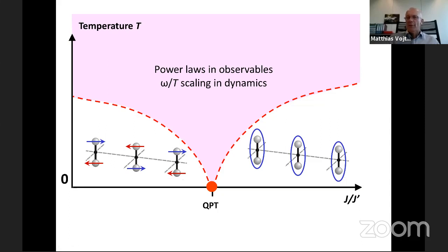There are various things one needs to consider. The first question, I guess, is does this ordered phase here on the left-hand side survive at all? If the answer is yes, there may be a different magnetically ordered state. For instance, instead of a square lattice, you can take a triangle lattice that's a bit frustrated, but there is still magnetic order. Then the phase diagram will qualitatively look the same. And since magnetic order is weaker, this phase transition point will move slightly to the left. So this phase tends to be suppressed with respect to this one. That is a quantitative change, but it's not very spectacular.